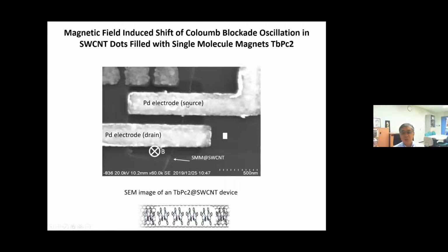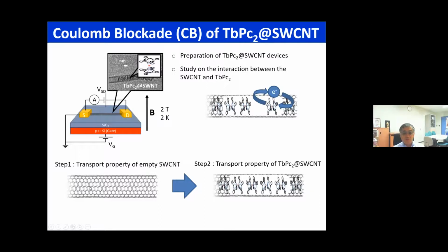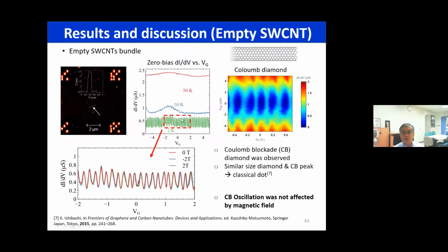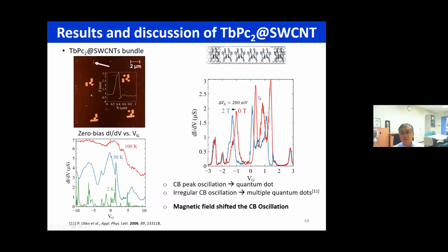This is a single carbon nanotube, and this is a palladium electrode. This is a motif of the terbium phthalocyanine inserted. This is the device before encapsulation, after encapsulation. We compared before and after of the Coulomb blockade. So before encapsulation, Coulomb blockade oscillation is observed, and we switch the external magnetic field. No difference, no magnetic effect because no spin in the single carbon nanotube. But after encapsulation, irregular Coulomb blockade is observed, and we increase the magnetic field. The magnetic peak is shifted. So this means that the conduction electron and the spin flip interact. So actually, single molecule magnet is inserted in the single carbon nanotube.